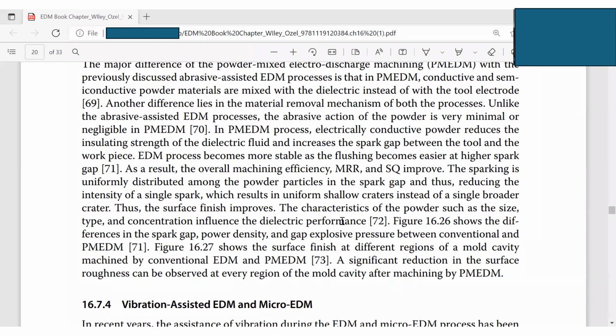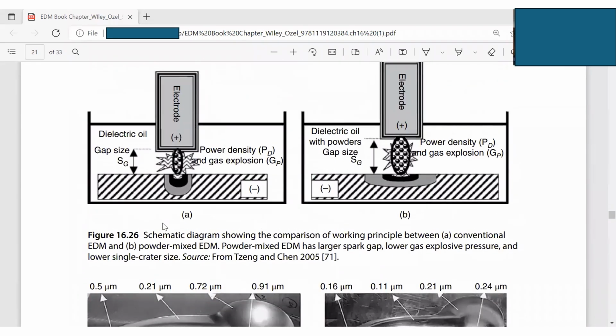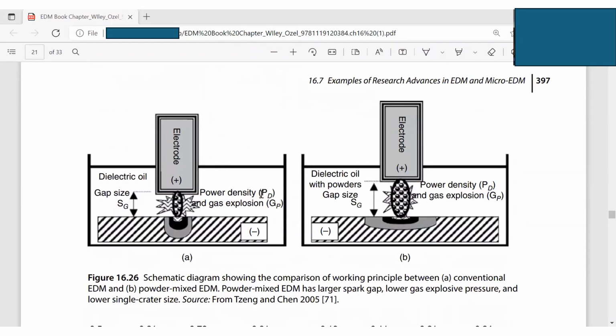So you can see this reference 72. This picture shows the differences in the spark gap, powder density, along with the gap explosive pressure, between conventional and PM EDM. So this is 6.26. Here, this is a conventional EDM, and this is the dielectric oil, the gap size between the electrode and workpiece, SG. Right? SG is the gap size, guys, and you write down SG is the gap size, and the powder density and gas explosion GP here.